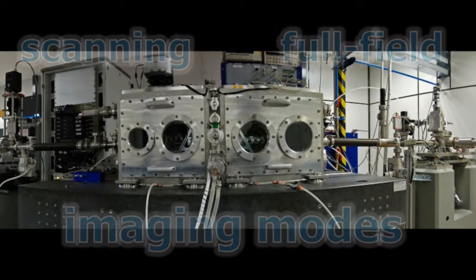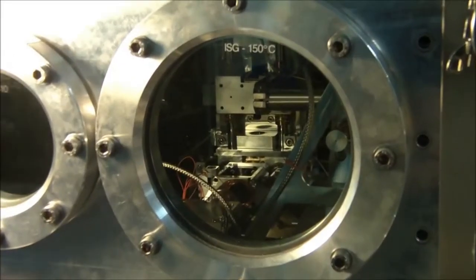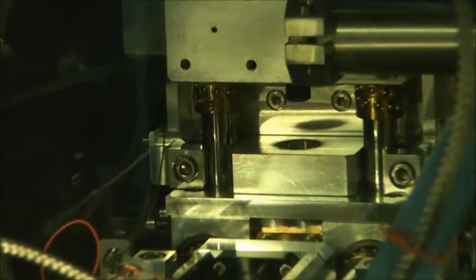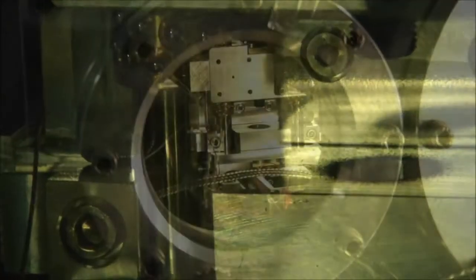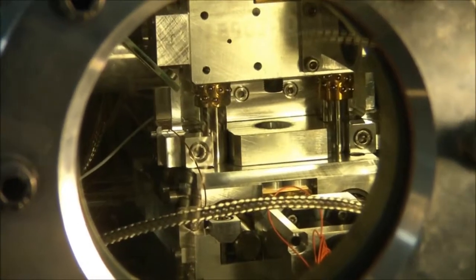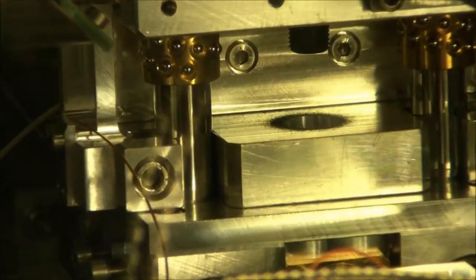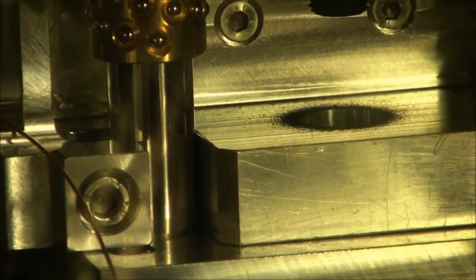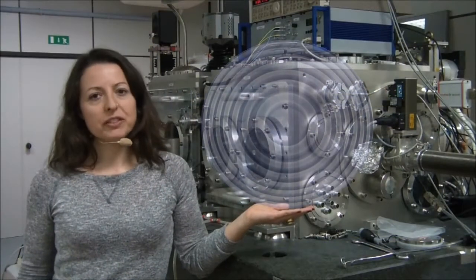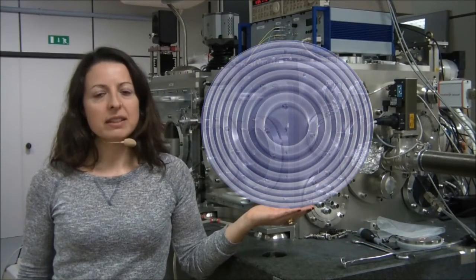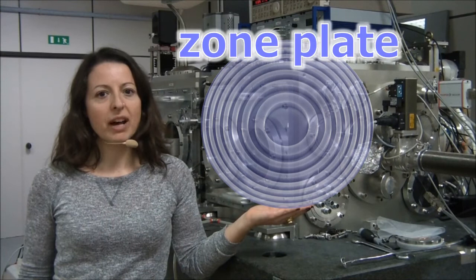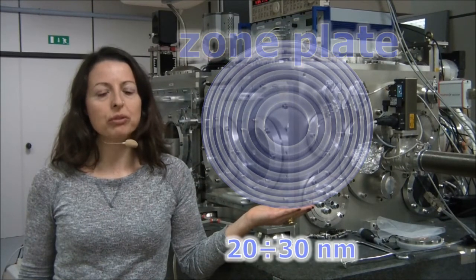The full-field mode is the analogous of the visible light transmission microscope, where a condenser lens illuminates the sample and an objective lens creates a magnified image of the sample. In the case of soft X-rays, the objective lens is a zone plate that can provide a spatial resolution of 20-30 nanometers.